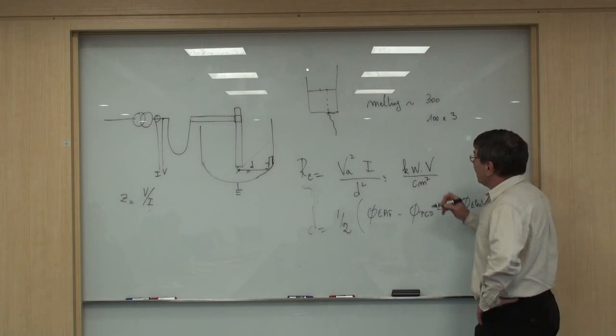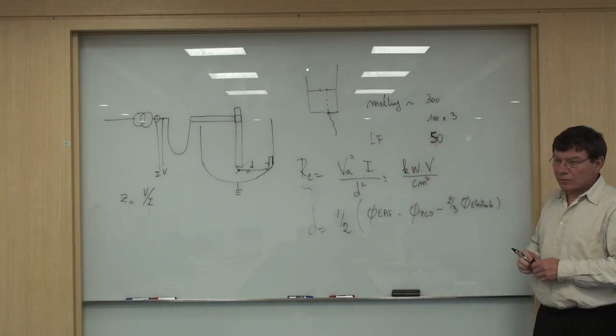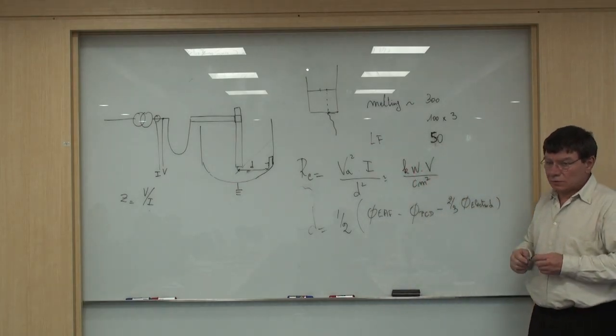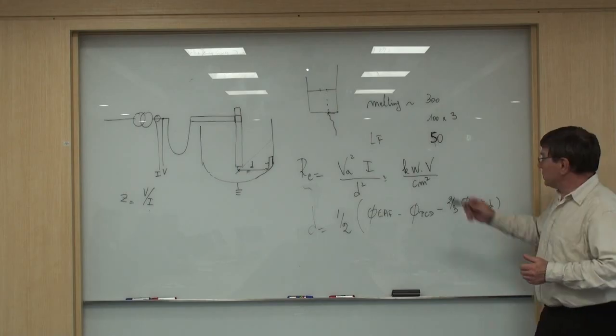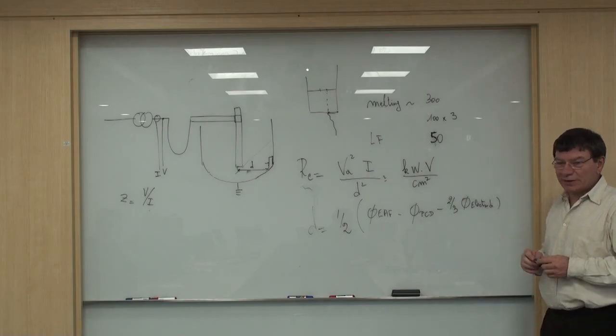Yeah. For ladle furnace, it's limited to 50. 50 is already a high value. This is the upper limit. If we can go lower, it's better.